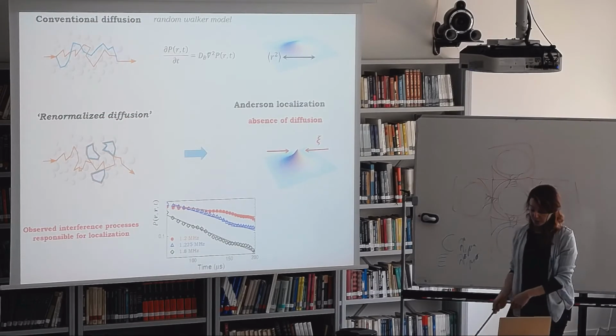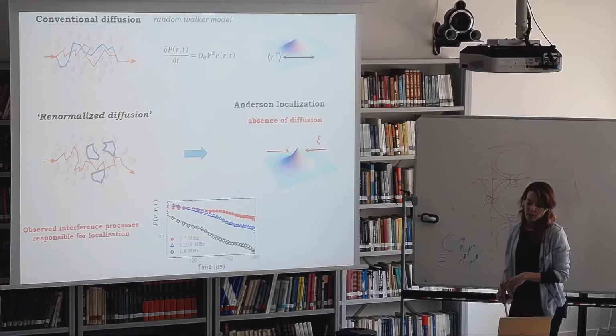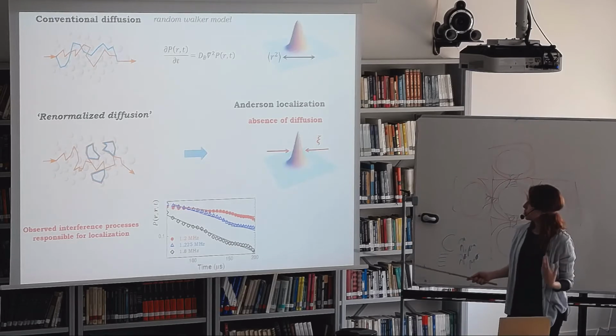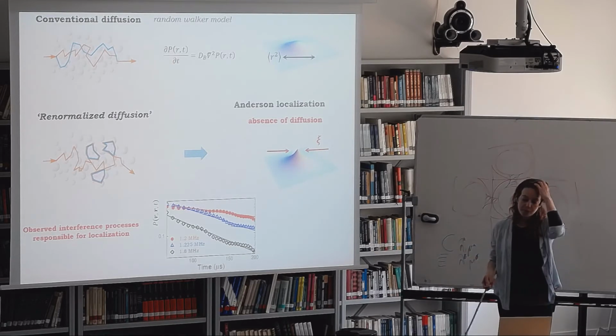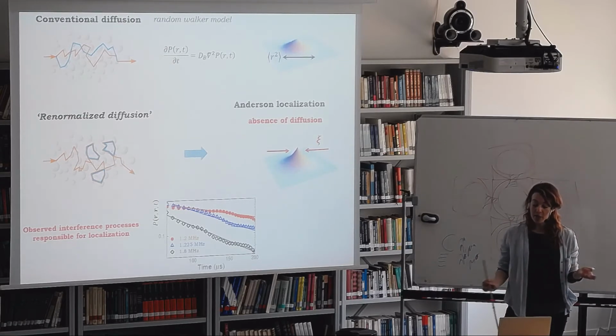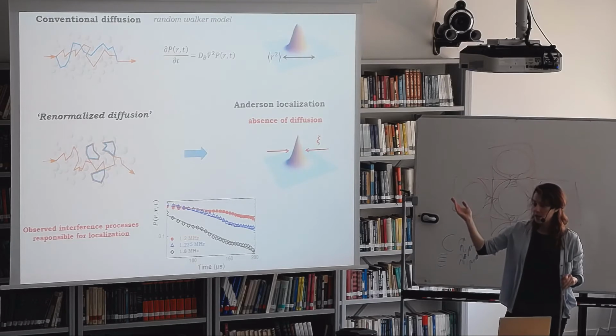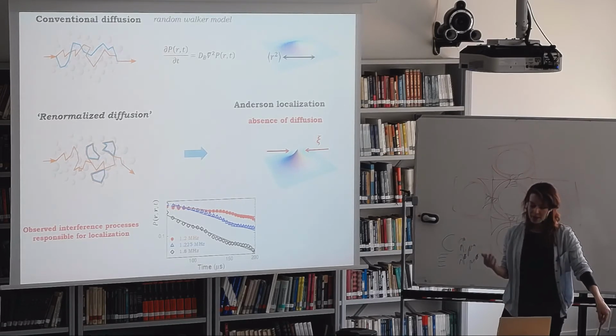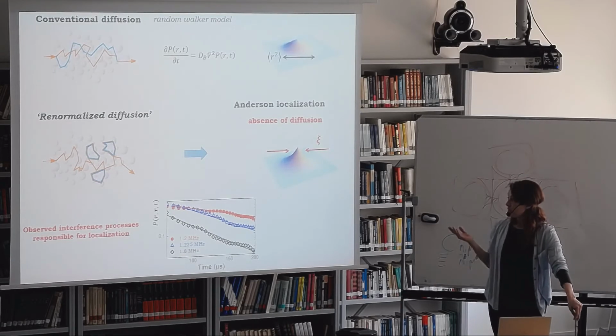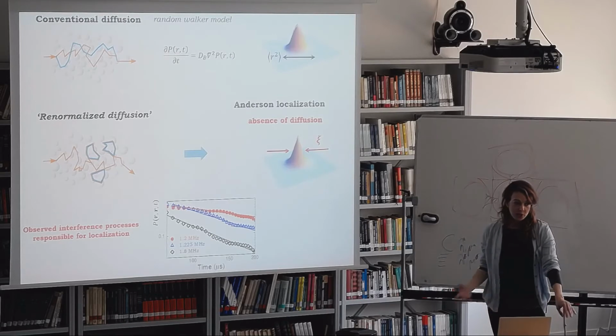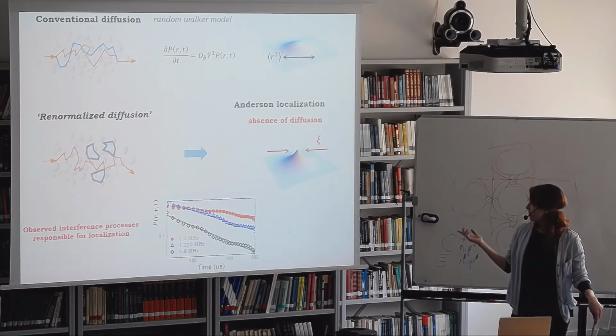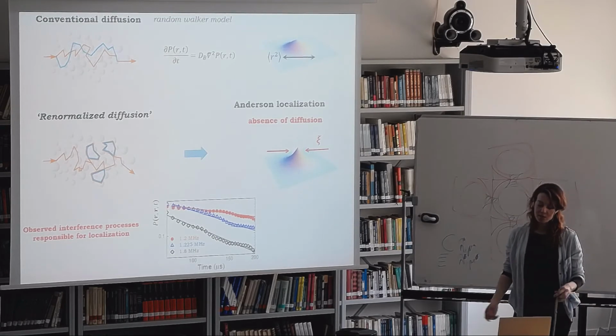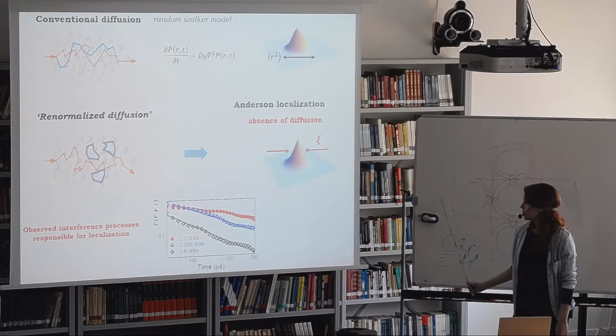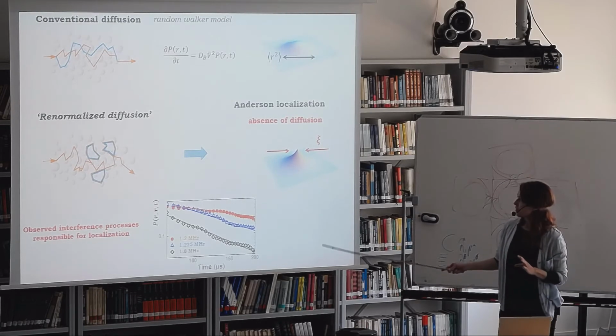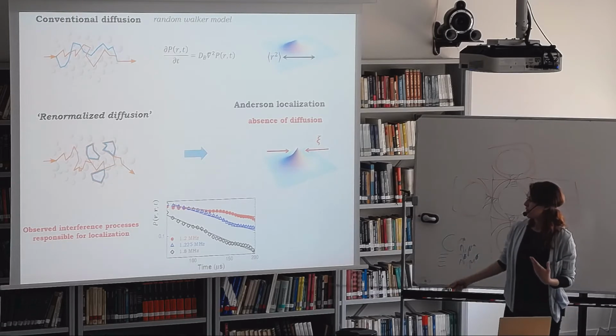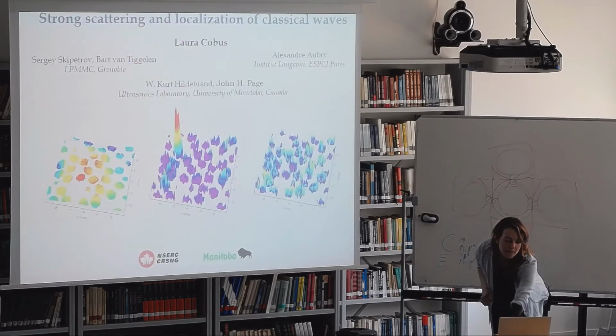Okay, so just to sum up, we've seen that in almost every situation, the multiple scattering of waves can be described nicely by the diffusion equation, which is based on a random walker model. And we can usually ignore the fact that waves have phase because we can describe the propagation using average quantities. But if interference becomes important, we need to take it into account, which one can do using a renormalized diffusion model. The most extreme end of the renormalized diffusion model is Anderson localization, so the absence of diffusion. And we can also observe rather directly these interference processes that are responsible for localization, such as the return probability. And that's it. Thank you.